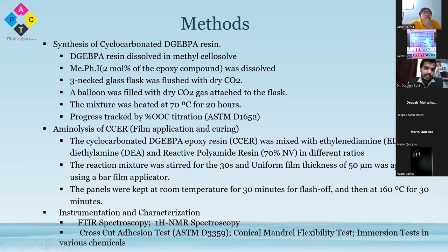Before starting the reaction, the three neck flask was flushed with dry carbon dioxide so that the air already occupied in the flask can be replaced by carbon dioxide. Then a balloon filled with carbon dioxide was attached to the flask. And this whole reaction was performed at 70 degrees Celsius for 20 hours. And progress was again tracked by percent OOC.